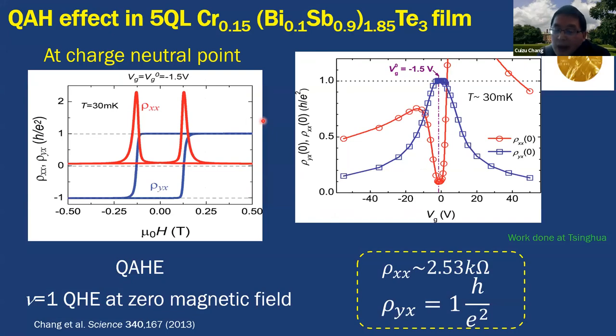And later, with many efforts, we tried more than 1,000 samples. And in 2013, we were the first to realize the quantum anomalous Hall effect in the chromium-doped bismuth antimony telluride film. So here is the magnetic field dependence of the Hall resistance. We can see that at zero magnetic field, the Hall resistance is almost quantized, and the longitudinal resistance is vanishing.